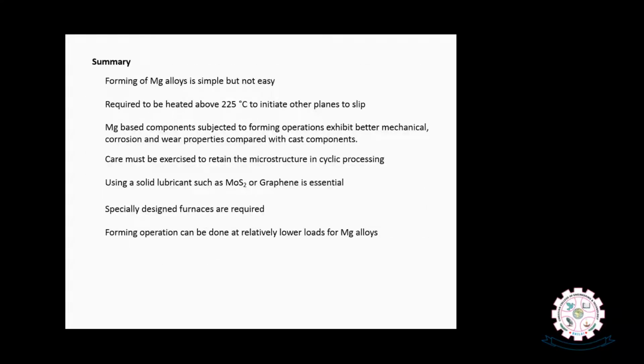In overall summary, when it comes to the forming of magnesium alloys, it is simple and can be formed, but not at room temperature. There are some difficulties involved with magnesium deformation. Therefore, it is required to be heated above 225 degrees centigrade, where the prismatic planes as well as pyramidal planes also get activated. Therefore, a sufficient number of slip systems will be available to plastically deform magnesium at high temperatures. So magnesium-based components subjected to forming operations exhibit better mechanical, corrosion and wear properties compared with cast components.